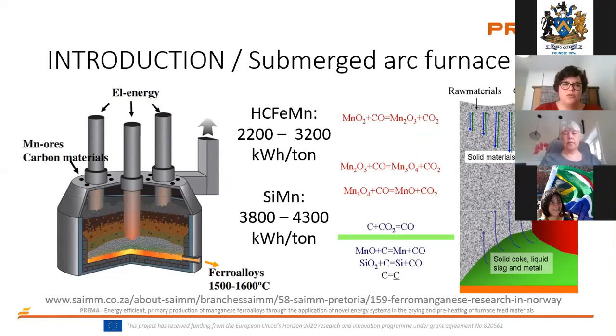In manganese production, the ores, carbon materials and fluxes are fed through feed pipes in the roof. And then what you see is a burden of material forming on top of what we call a coke bed, which contains coke and slag, and then the alloy layer. So this burden of raw material, as it moves down towards the bottom of the furnace, a gas reaction takes place. So your higher oxides of manganese and iron get reduced.